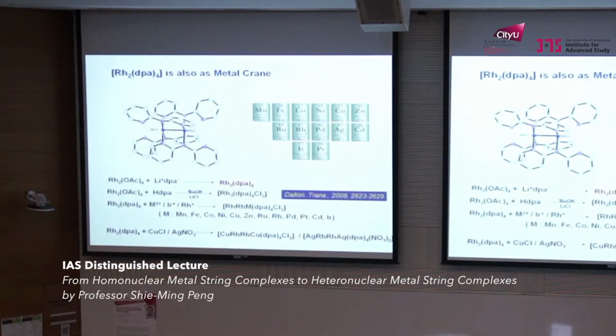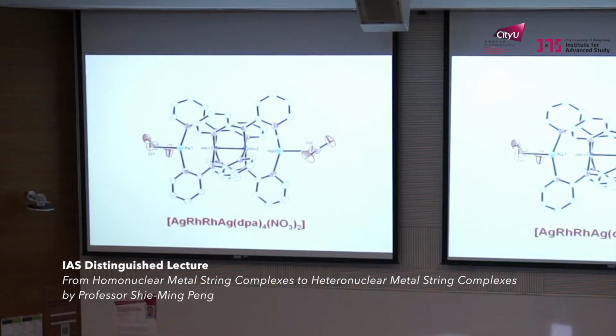Another clamp is dirhodium. Dirhodium has a structure of 2-2 trans, with two pyridyl on one side and another two pyridyl on the other side. But still, they can clamp, they can catch the third metal ion, with rhodium metal, in almost the same series. Of course, you can think the mechanism is that when they coordinate or catch one ion, the other two ligands will have a 1-2 shift to get the compound. Okay, so here are some compounds. Even the two can be silver, rhodium, silver.